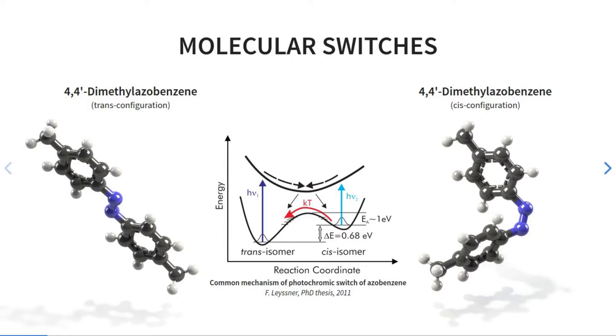First of all, let me tell you which molecule is the focus of my research and which part endows the molecule with the light sensitivity. I consider the azobenzene-based switch. As seen on this figure, the energy of the ground state is characterized by an asymmetric double well potential. Azobenzene is excited by UV light from ground to excited state, then it changes its geometry. The excited state falls back to the ground state by inversion or rotation of a double nitrogen bond and relaxes in either trans or cis form by a symmetry breaking phase transition. And this energy barrier of one electron volt allows a direct thermal transition from cis back to the trans configuration.